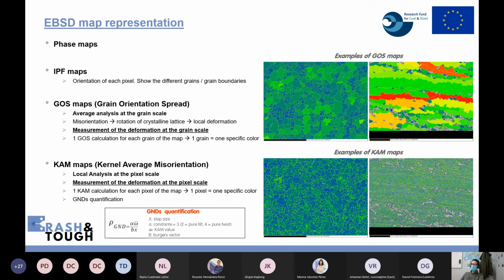So through the GOS, we are able to see if the grain is deformed or if it is recrystallized. For example, this is a microstructure fully recrystallized, and this is a microstructure deformed with some elongated grains.